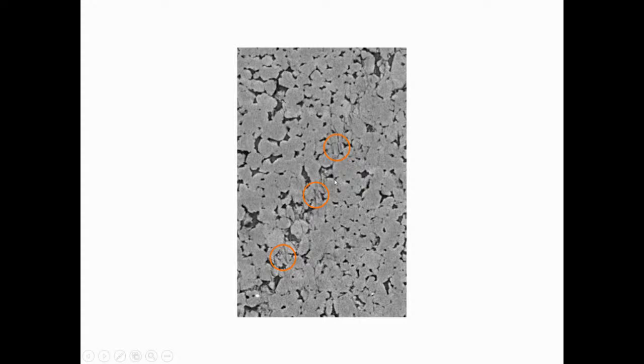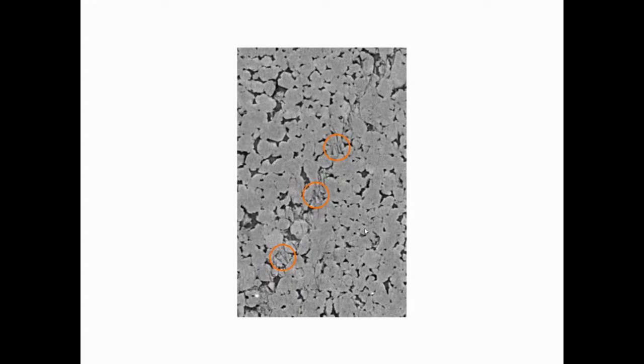Yeah, indeed. And then you can see that initially you've got these tensile cracks, you've got some shear on the grain boundaries, and you've got a bit of rotation. The grains are rotating to enable coherent slip to occur. And the intact rock is staying pretty much where it is. There's not much damage outside the shear band once you get localization. And then in some cases, it even over-rotates. So now this fracture is shearing in the conjugate direction. Everything else is shearing in this sense, and now this one is shearing in the opposite sense because it's over-rotated.